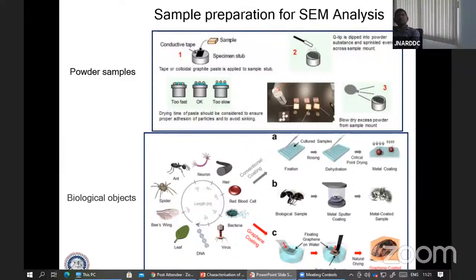First of all, we have to grind our powder sample, then crush it, and then take one specimen stub here. This is a metallic stub upon which we have to paste one carbon tape. It's a conductive, adhesive tape. Upon that, we sprinkle one pinch of powder and then blow off the excess powder, so that any excess powder that is detached from the carbon tape is removed. Then we can use this stub and it is ready for our SEM analysis.